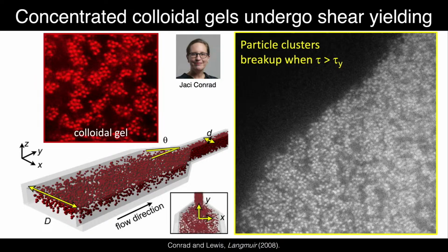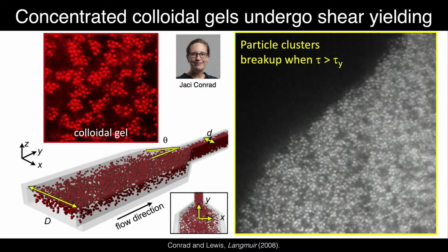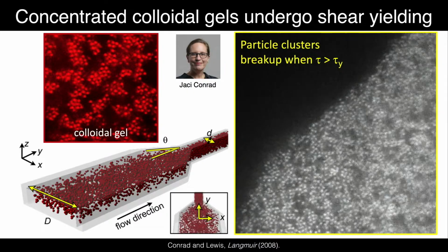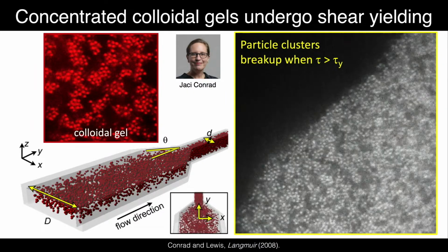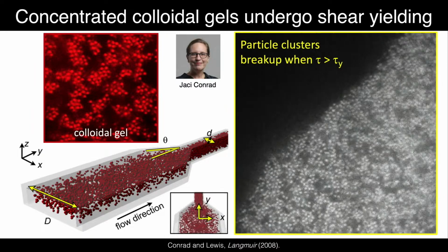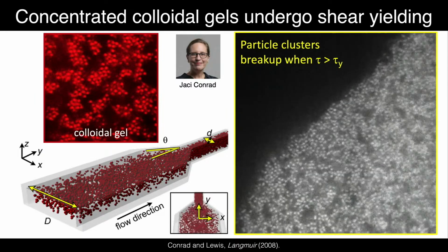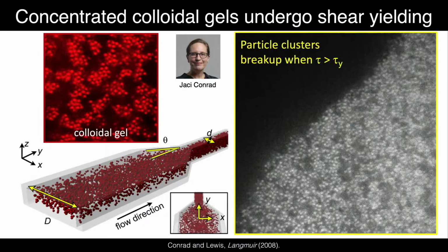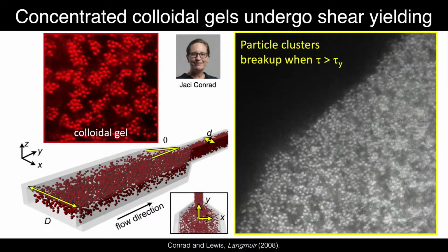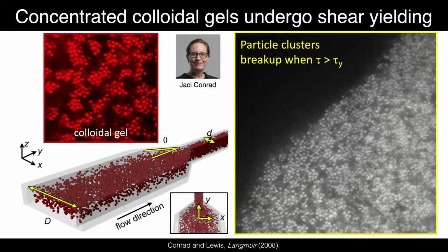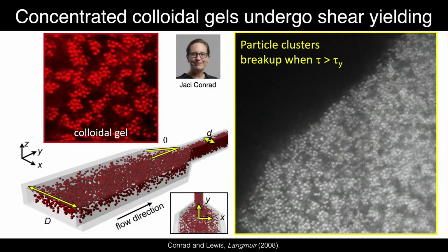And so we made this very nice mimic of a nozzle, a microfluidic device. And you can see that these little particles, we can actually introduce fluorescent cores. We can track them. And this is just looking at an edge in a region where you're turning down from, say, the ink barrel to the nozzle. And you can see that under shear, these particle clusters start to break up. But when you take the shear away, they rebuild very quickly. And this spanning network is really what's giving it its solid-like properties.